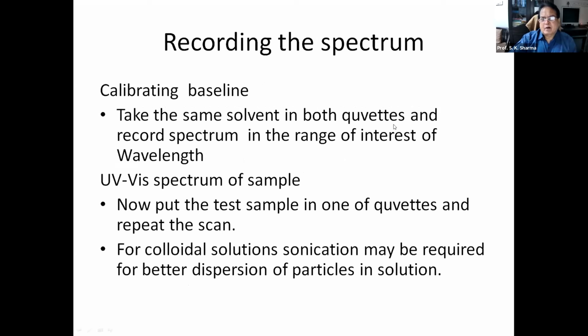Then, for recording the spectrum, what we have to do first is calibrate the baseline: take some solvent in both the cuvettes and record the spectrum in the range of interest. And for recording the spectrum, we put the test sample in one of the cuvettes and repeat the same scan. For a colloidal solution, sonication may be required.